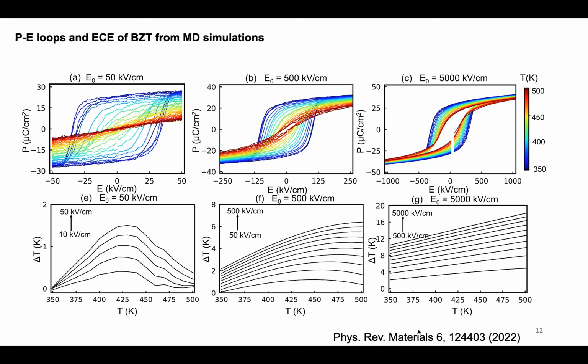And once we increase the amplitude of the field, going from 50 to 5,000, the loops are not closed. The films are still in the ferroelectric phase. I mean, the system, the supercell, is still in a ferroelectric phase. And we calculated, using the indirect approach, the change in the temperature for all these amplitudes of the fields. So you can see the peak of the electrocaloric loop shifts from the desired temperature range. We know that this has already been observed, Professor Cohen, 10 years back.